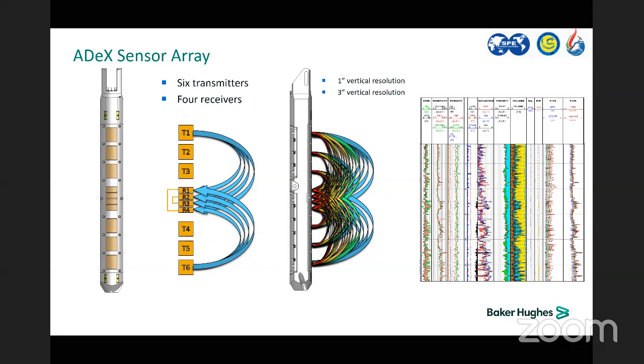So what we did, we enhanced the pad design to have a good contact, and we also enhanced the tool itself to avoid the noise coming from the conductive fluids. So we succeeded in getting good data with this modification. Yes, we came late, maybe after 7 years from the first dielectric, but we tried to make sure that the tool would overcome all the challenges. So if you heard before that in low resistivity pay the dielectric will not help because the resistivity is low and the dielectric will be noisy, this has been overcome by the tool modification I have mentioned.